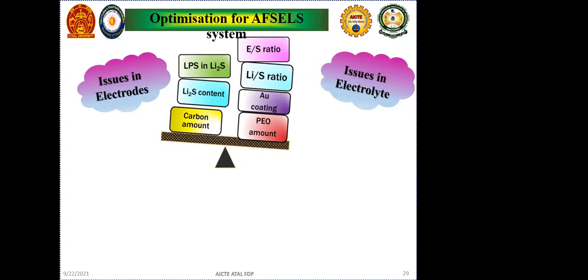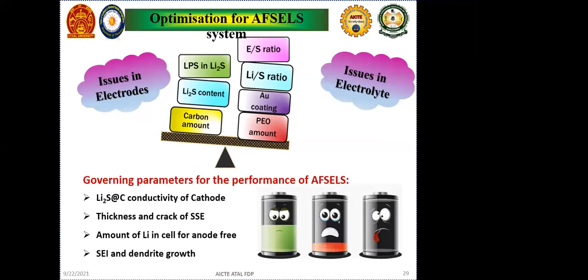Similarly, when I go for the anode free current collector, if I can go for coating of metal, or coating of some polymer, then when I coat the other material on the current collector, it can trap the lithium in a proper way, and also prevent the dead lithium formation on the surface of the current collector. So if I keep this scheme in mind and go for work in an anode free solid state lithium sulfur battery, then definitely I can focus on developing a better solid state lithium sulfur battery.